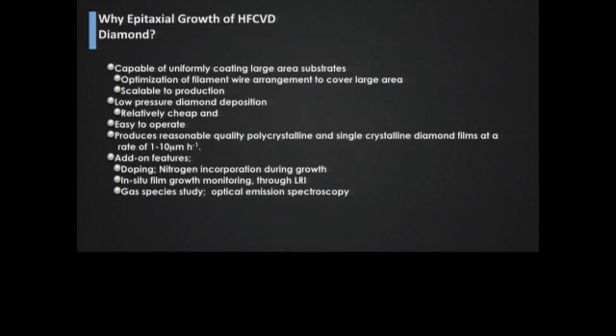We can do low pressure deposition. It's really easy to operate. The students can learn how to operate it pretty quickly. It can do both polycrystalline and single crystal materials. And we've added a lot of doping, so nitrogen doping, the in situ growth measurements, and of course the gas species study, which we can use optical emission spectroscopy to do. So those are some of the things that we have added, and this is sort of our argument why we have invested in the hot filament versus the microwave plasma approach.